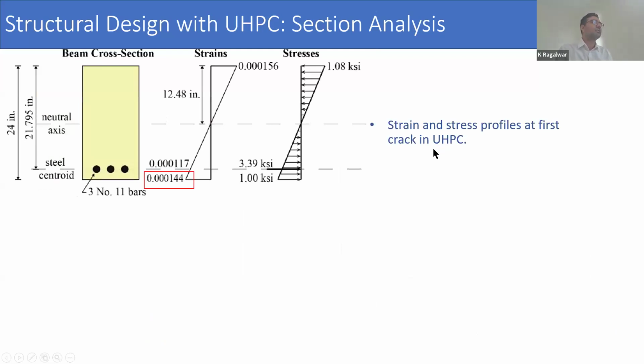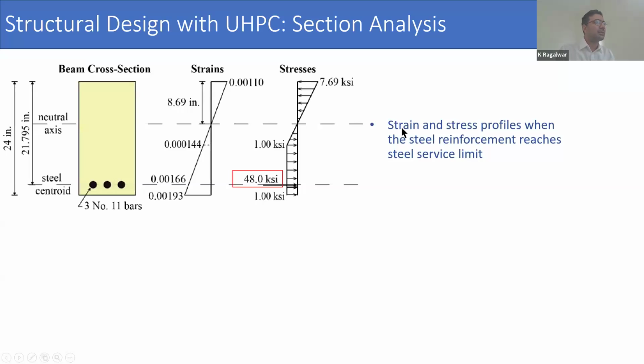So this is the first point in our plot, if you remember moment versus curvature. What we define in the first plot is that we put the strain at the extreme bottommost fiber equivalent to the cracking stress. That would give us a strain distribution. Based on that strain distribution, we calculate stresses, and we evaluate the moment based on that. The second evaluation point is where we equate the stress in the steel reinforcement to the service limit. Now, the service limit in ACI or AASHTO is defined as 0.8 times the yield value. The yield strength of this reinforcement is 60 KSI, so that would give us 48 KSI.